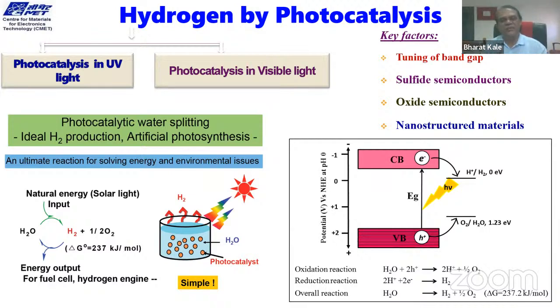Or the nanostructuring, because nanostructuring really helps in electronic phenomena, because you see that the surface area gets increased and maximum sunlight can be absorbed, and the photo excitation is very easy in the nanostructured material. Like you can see the size quantization effect is much more efficient, and it will really help in this photocatalysis. So it's a simple water splitting process where you can see it's a simple photocatalyst which absorbs sunlight and produces electron holes.